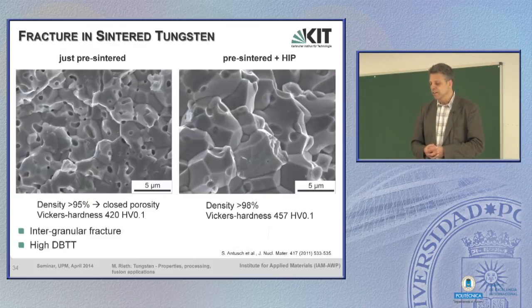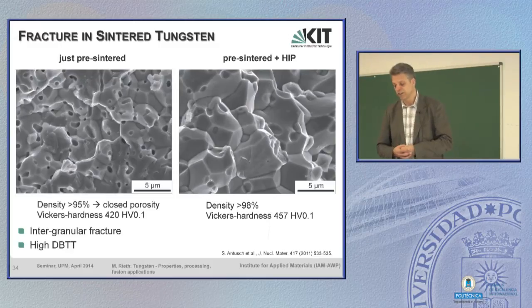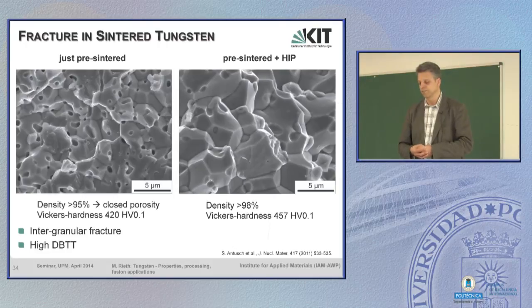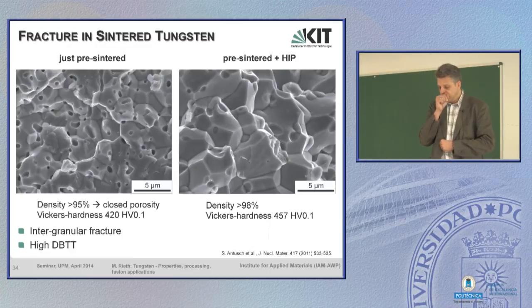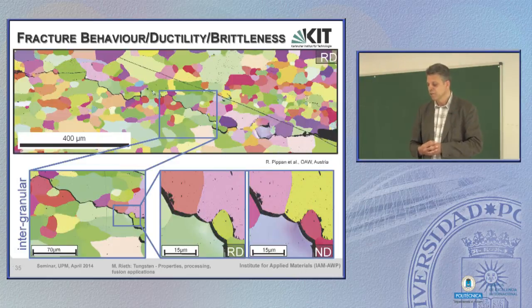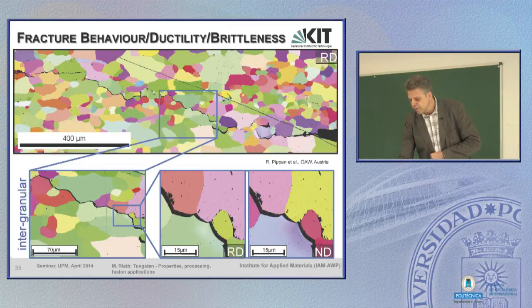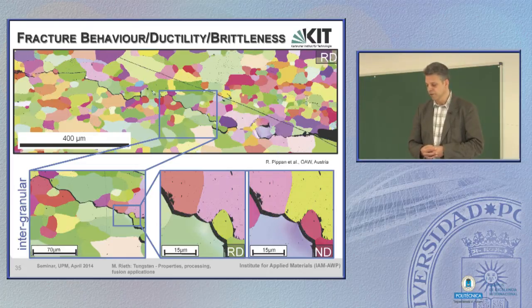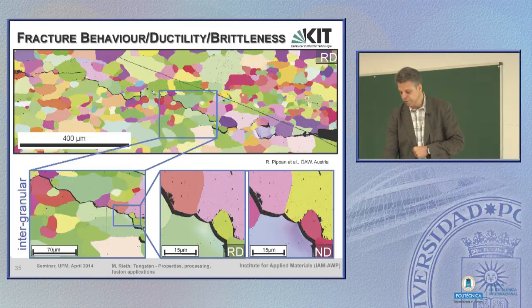Now let's come to the fracture in the sintered tungsten. Sintered tungsten, as mentioned, does not have a very high density. It varies somewhere between 90 and 100%. Nevertheless, it shows almost always intergranular fracture, and as you have seen, there is a rather high DBTT, if at all. We haven't performed tests higher than 1100 C, but up to 1100 C there was no ductile fracture. So most often we see this intergranular fracture, and if you look at this grain, only sometimes we observe transgranular fracture. That's a general fracture behavior of tungsten.